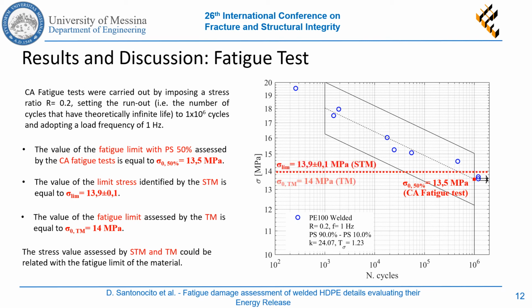On the other hand, the limit stress estimated by the static thermographic method with only 3 specimens is equal to 13.9 MPa, while the fatigue limit estimated with the thermographic method on 2 specimens is equal to 14 MPa. These values are in very good agreement with the fatigue limit assessed by traditional fatigue tests, showing how it is possible to estimate this value in a very short amount of time.